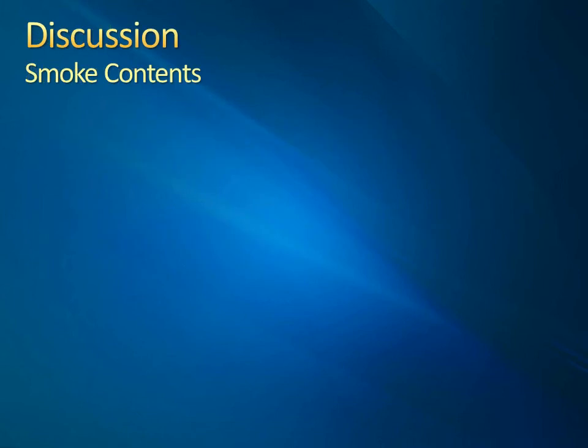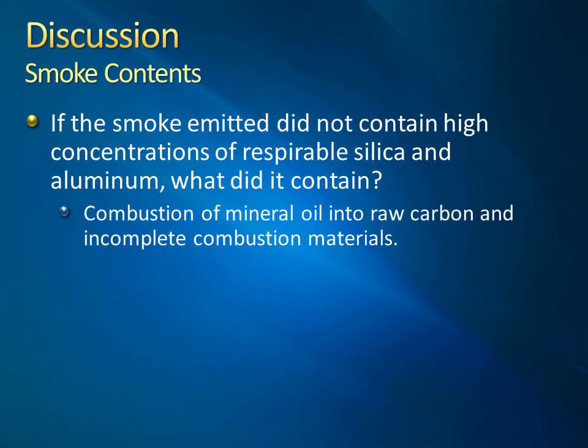The haze and smoke emitted during the molten metal pours into the green sand castings was assumed to contain much greater quantities of the target analytes. Without performing a composition analysis of the smoke for a wide range of materials, the smoke composition can only be speculated. The green sand's binding compound was pre-mixed mineral oil, a mixture of heavy alkanes distilled from petroleum. When the high temperature molten metal hits the green sand, the mineral oil coating the sand undergoes incomplete combustion, forming carbon monoxide, carbon dioxide, and soot, raw carbon molecules. Depending on the amount of oxygen available, the smoke particles would perhaps be an amalgam of combusted alkanes and this raw carbon.